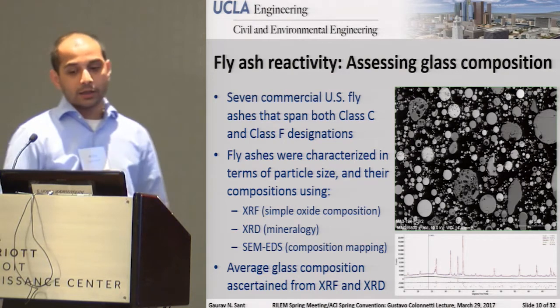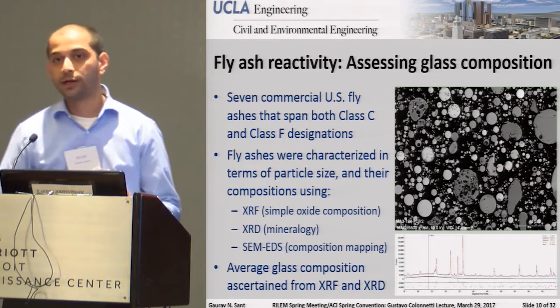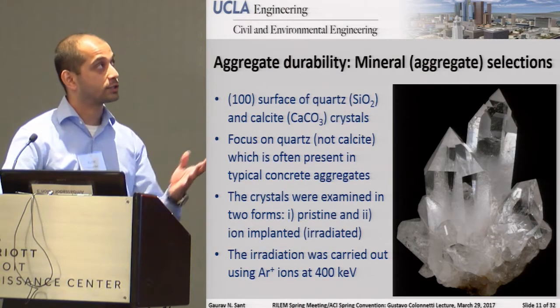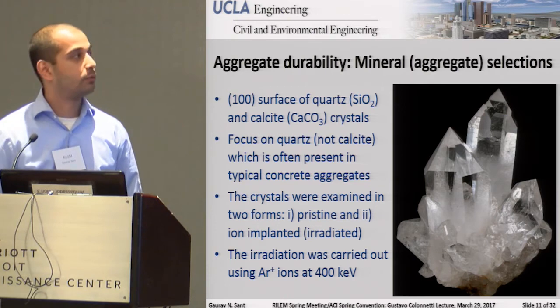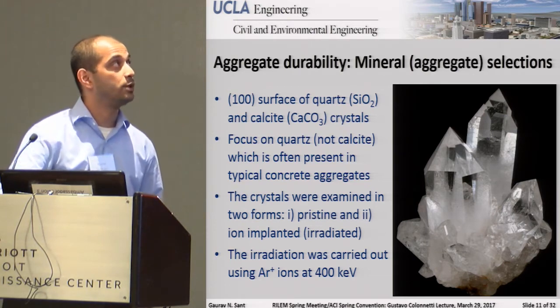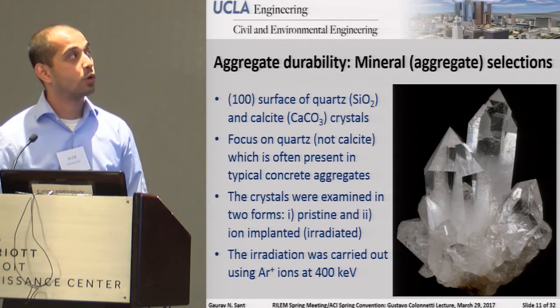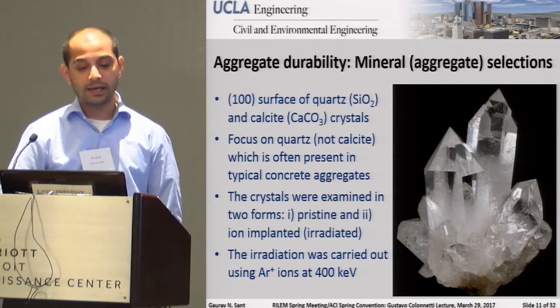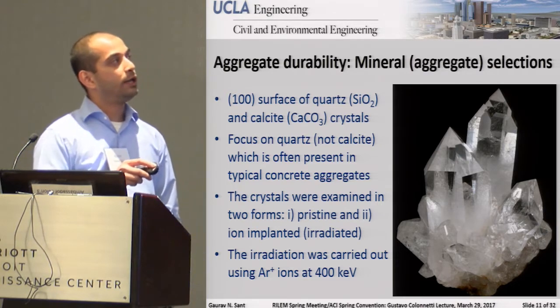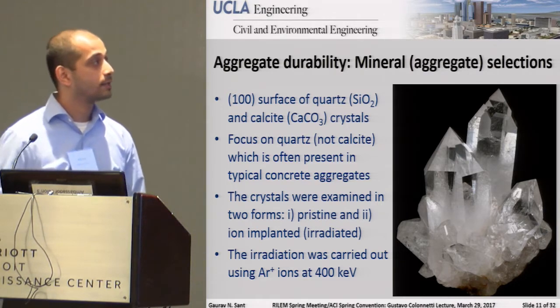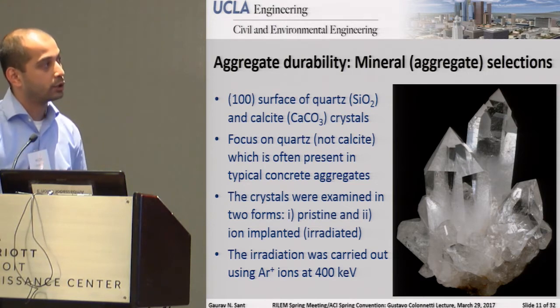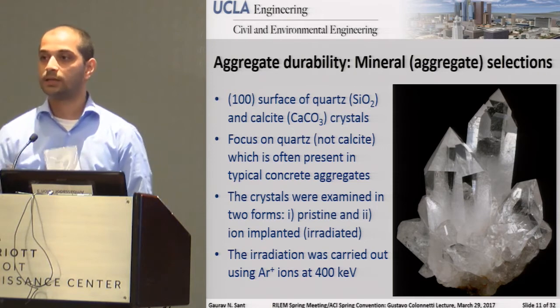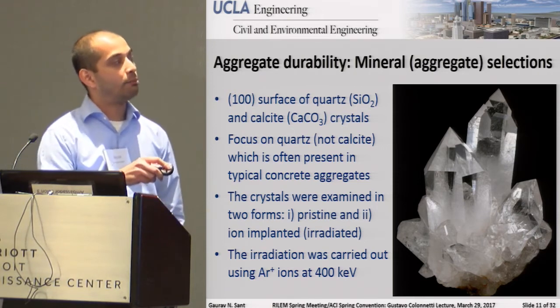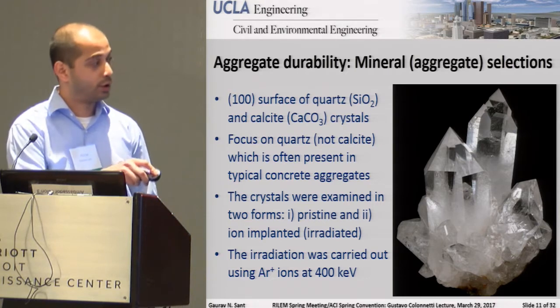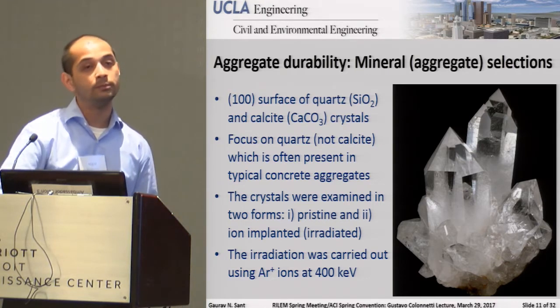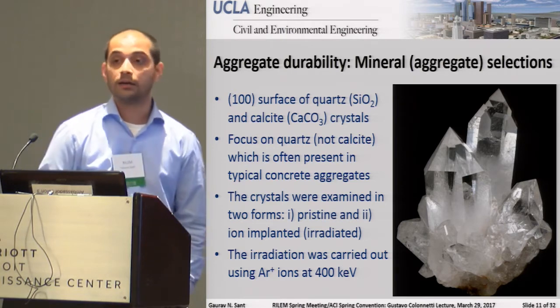Now, with regard to the aggregates, we took a slightly different approach. While in the context of fly ash we were trying to stick much more with, I would call it, reality, in the context of looking at aggregate durability, we took a much more synthetic route. So specifically, we started with looking at 100 surfaces of quartz and calcite. We were looking at quartz and calcite because they're often present in concrete aggregates. I'm not really going to focus on calcite since I'm going to try and stick to the theme of silicates. But we looked at these crystals in two forms. So we looked at them in what I will call a pristine form. So they were used basically as is, as synthetic single crystals. And then we ion implanted them. So basically, we took a heavy ion gun. We were using argon ions accelerated at 400 keV, and we were impacting them onto these single crystals.